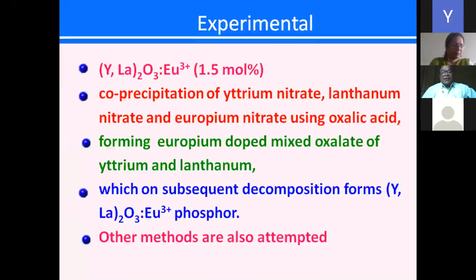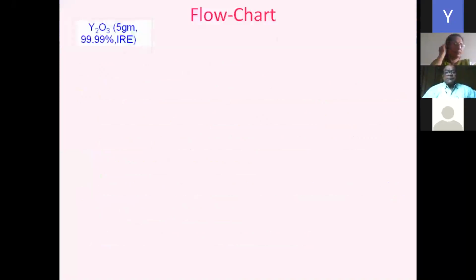And we have prepared all these samples by co-precipitation, not solid state synthesis or solid state diffusion: co-precipitation of yttrium nitrate, lanthanum nitrate, and europium nitrate using oxalic acid. Then forming europium doped mixed oxalate of yttrium and lanthanum, which on subsequent decomposition forms (Y,La)2O3:Eu3+ phosphor. Other methods are also attempted simultaneously. This is the flow chart.